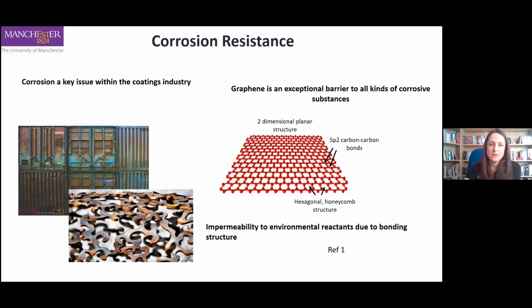The reason it helps with anti-corrosion, again, is down to its structure. So if you look at the diagram again of graphene, the bonding arrangements of the atoms are important, and also its incredible chemical stability. The hexagonal arrangement has pores in between the hexagons, and these are tiny. These are less than 3 nanometers. And the way that the orbitals are arranged in this bonding configuration means that graphene has a delocalized electron cloud on it due to these double bonds, this pi conjugation, and this provides a repellent field almost and helps to block these pores even further.